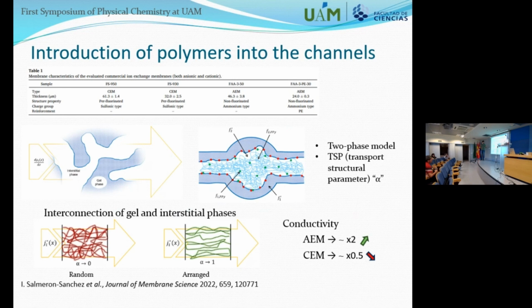What was the reason for that? What was proposed in the work is that in the cation exchange group, we have negative fixed charges in the channels, and then the interaction of the polypyrrole with these channels reduces the availability of the ion exchange groups, and thus we reduce the effective ion exchange groups, and then we reduce the conductivity. Anyway, with both of them, because we are filling the pores, we are also reducing somehow the pore size, and that helps to reduce the crossover of the active species. So it's a very interesting approach also for this type of membranes.